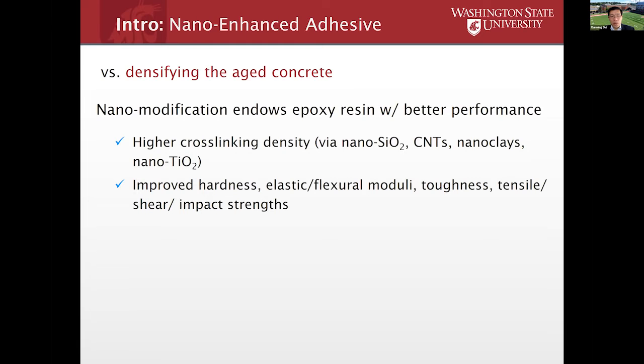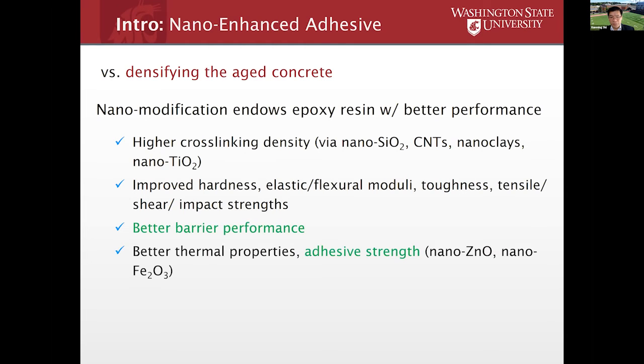So we know already that nano modification could endow epoxy resin with better performance. There are lots of studies out there, for instance, using nanosilica, carbon nanotubes, nanoclay, or nano titanium to give epoxy higher cross-linking density, or sometimes better mechanical performance in terms of improved hardness, modulus, toughness, strength, and so on. Now, in terms of durability, what's highly desirable is that nanoclay is a 2D nanomaterial, so it gives better barrier performance of the coating layer or the adhesive layer, and also better thermal properties and better adhesive strength.